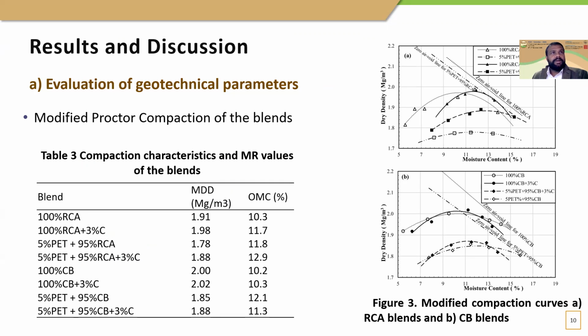Moving on to the modified Proctor compaction of the blends. The modified Proctor compaction of unbound and 3% cement stabilized blends are presented in the figure. The maximum dry density values of the cement stabilized blends are higher than the respective unbound blends. The fine cement particles can fill the voids in blends and increase the MDD, or maximum dry density, of the blends, producing better compaction. Adding 5% PET to blends has reduced the MDD values and increased the OMC values of the C&D materials.